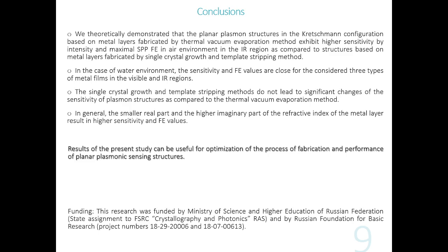So, as a conclusion of our study, I can say that it was demonstrated that the method of fabrication can lead to remarkable deviations in resonance characteristics in the case of non-absorbing media. In the case of non-absorbing media, in particular air, we saw that there is some increase in field enhancement, which could be useful for fluorescence enhancement applications, and an increase in the sensitivity, which is good for biosensor applications in the middle infrared region.